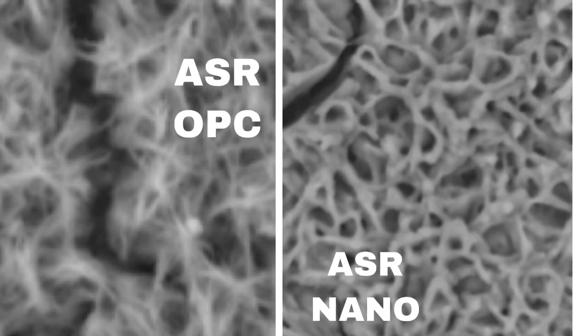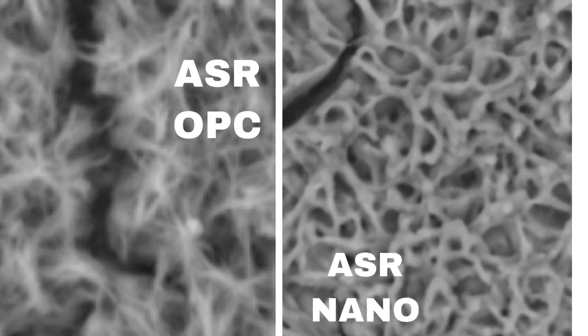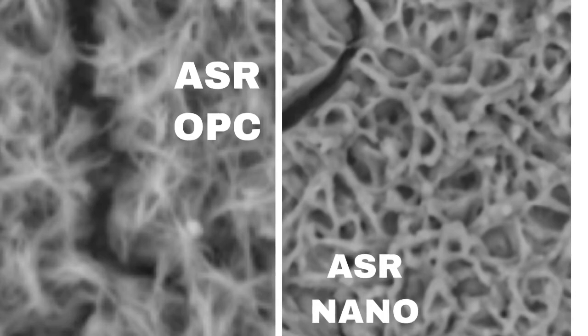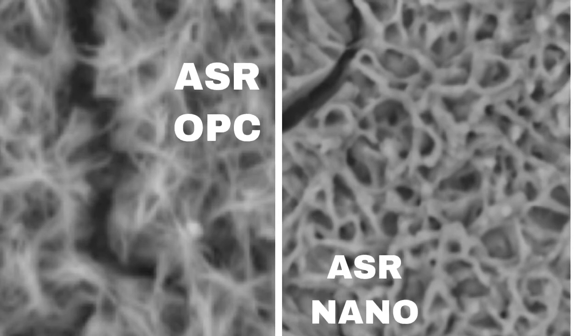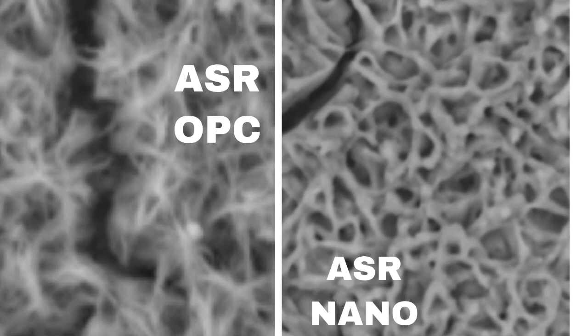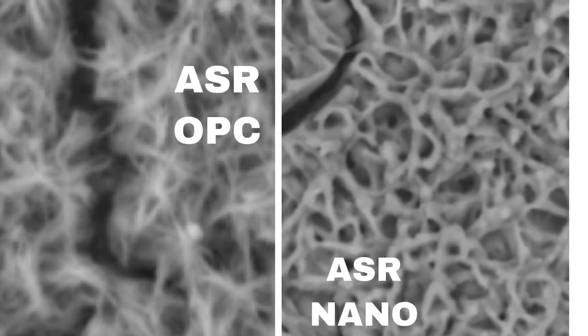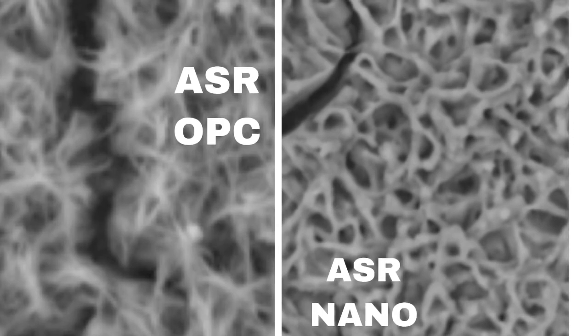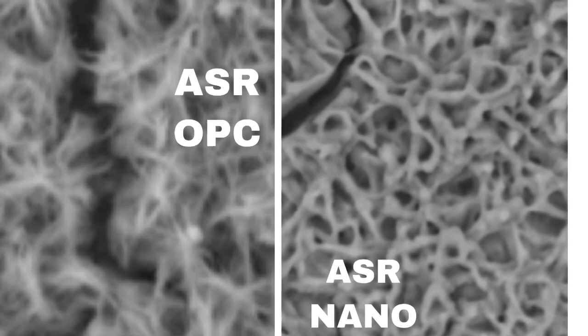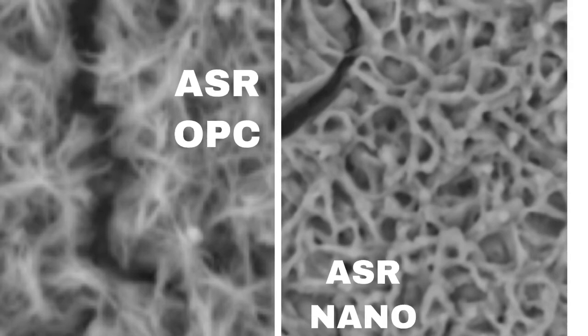It really is quite exquisite to see this change in structure. With that larger opening, you don't have that capillary absorption. When we were doing the environmental scanning electron microscope analysis, we also used energy dispersive X-ray analysis to look at the mass species of the gels. What we found is with the nanosilica-enhanced mix, you had less calcium in the gel, less sodium, less potassium, but more silica. We did some concurrent tests using ASTM C1567 and C1260, and what we saw was a lower degree of expansion. So we're robbing the alkali silica gels of the alkalis but feeding it the silicas, ultimately getting past the pessimum — the environment where this ASR gel can thrive and survive.